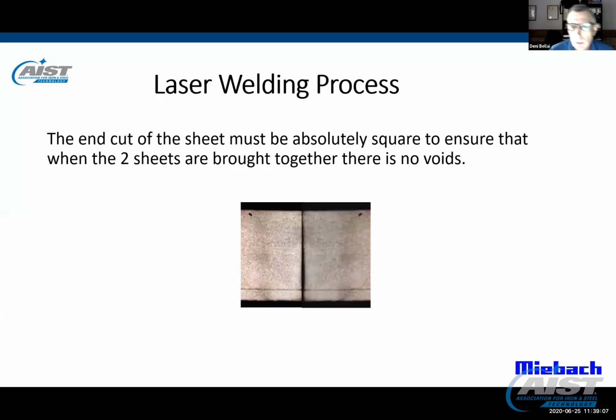So the laser welding process requires very accurate and precise positioning of the strip and the laser beam. Starting with the cut profile, it must be nearly perfectly square, so when the sheets are brought together, there is a tight fit and minimal voids in the gap.